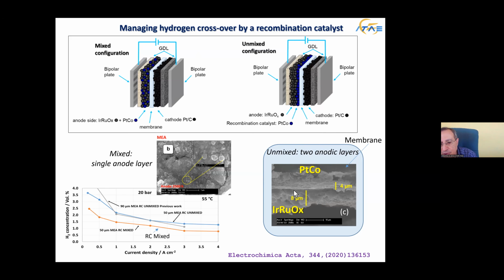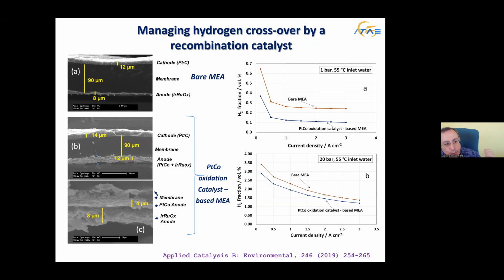Using this approach, we can achieve high differential pressure operation - that means pressurized hydrogen, non-pressurized oxygen. Why pressurized hydrogen? Because we need to reduce the energy consumption in the downstream compression of hydrogen. This is a clear example: using this recombination catalyst and a bilayer MEA, we have a much lower concentration of hydrogen in the oxygen stream at the anode in the presence of the recombination catalyst. This is the dual layer that is perfectly operating for recombining this hydrogen.